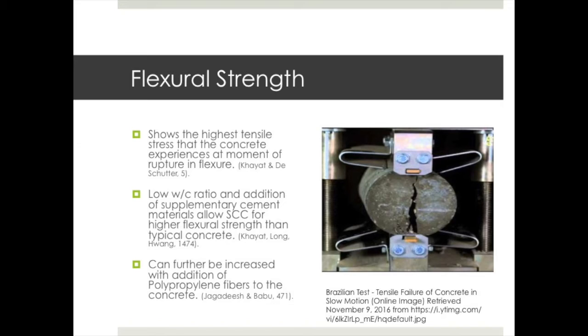Flexural strength is an important topic of SCC's mechanical properties, as it shows the highest tensile stress that the concrete experiences at the moment of rupture and flexure. Due to the addition of supplementary cement materials and the low water-to-cement ratio required for SCC, it is understood that SCC has potential for a higher flexural strength than typical concrete. Flexural strength of SCC can also be increased with the addition of polypropylene fibers to the concrete.